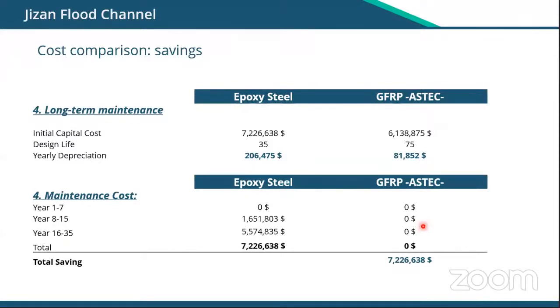The biggest beneficiary of switching to GFRP is definitely the owner. And that's very obvious on this graphic. This is information from the owner. If they design a marine structure with epoxy coated steel, they only design it for 35 years, while with GFRP, they design it for 75 years. So you need to rebuild the structure at least once with epoxy coated steel compared to going with GFRP.